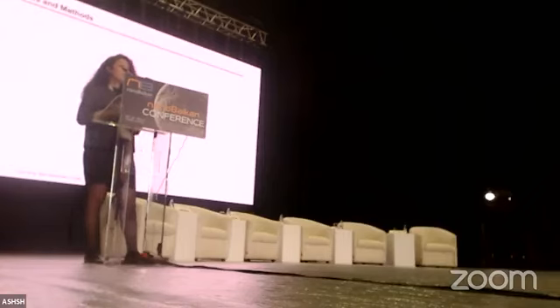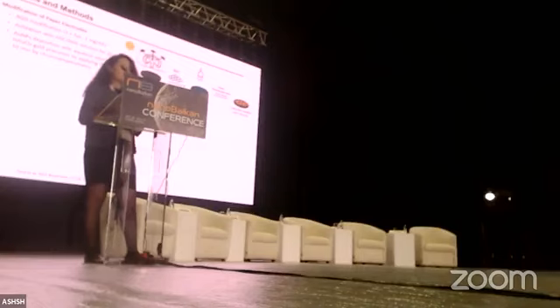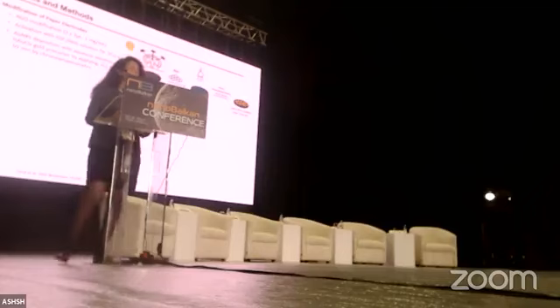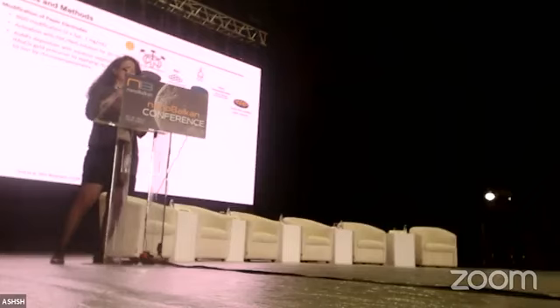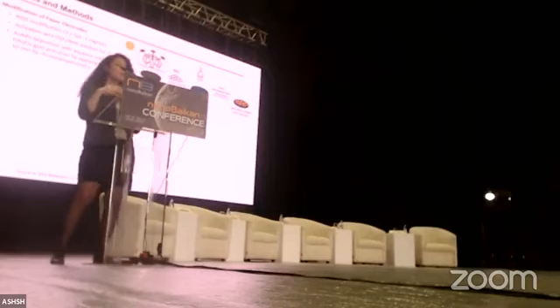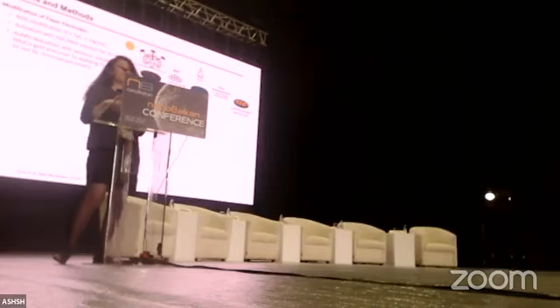Here are the details of our materials and methods. We started with the modification of the electrodes, of course. These are the electrodes we have, and the working electrode surface was covered by drop casting with reduced graphene oxide. Then EDC NHS was used as a cross-linking agent to activate the surface. Then the reduced graphene oxide surface was treated with a gold precursor solution, and the electrodeposition technique using chronoamperometry was used to cover the surface.